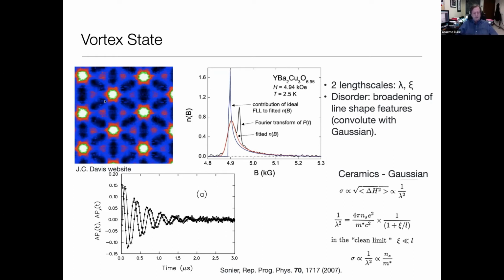And these supercurrents then die off as you go away from the vortex on a length scale given by the London penetration depth, which is how magnetic fields screen out at the boundary between a superconductor and a normal material. So there are three length scales in a superconductor in the vortex state. There's the lattice constant for the magnetic order, which is determined by the magnetic field you applied. There's a length scale over which the superconducting wave function varies, which is essentially the vortex size, or the separation on average between two electrons in a Cooper pair. That's the coherence length. And then there's the magnetic field penetration depth, which is how magnetic fields are screened away from a normal material. And that's the penetration depth.